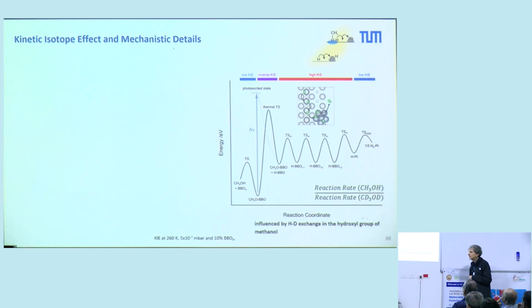Then we have, of course, the photo formation of the aldehyde. Here we don't expect a large isotopic effect because we have a lot of photon energy, and so the small differences in zero-point energy of the different isotopes are negligible. We even expect a negative one because we have another reaction channel taking place. Then we have, of course, the diffusion. Here we have a larger isotope effect. Then for the recombination of hydrogen, again we have a small kinetic isotope effect. This has been measured on single crystals.